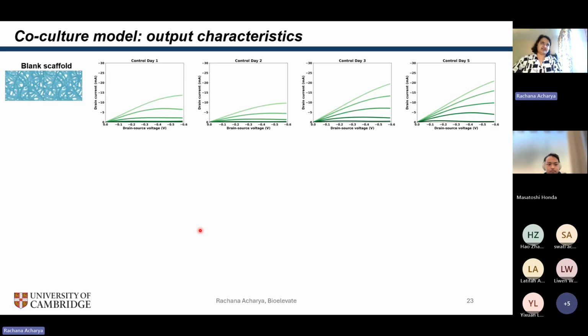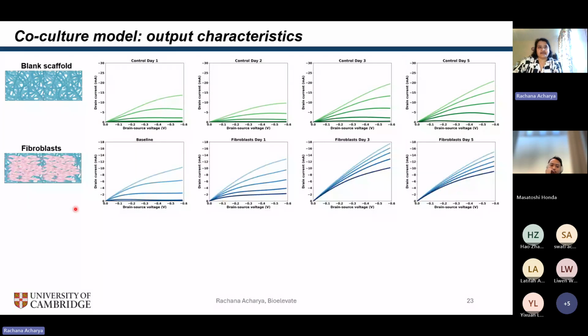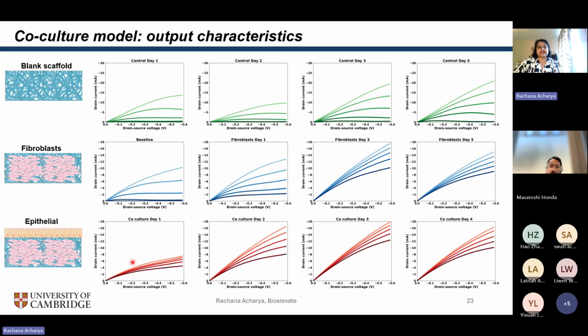So let's start with our output characteristics, just like we saw for our fibroblasts. Just as a quick reminder, if I have a control, which is a blank scaffold, I have a consistent switching off behavior in my device. If I grow my fibroblasts, I see that the switching off of the device is impacted, and I have this large off current as well. What happens when I put down my epithelial cells? I see that on day 1 of this co-culture model, I have a decrease in my drain current compared to my fibroblasts. But then the device stabilizes, and I don't have much of a change either in my on-off current ratio or in my electrical characteristics.